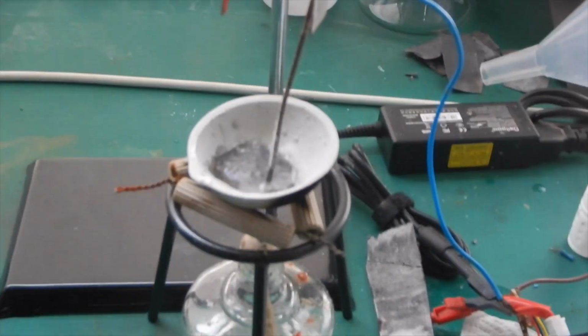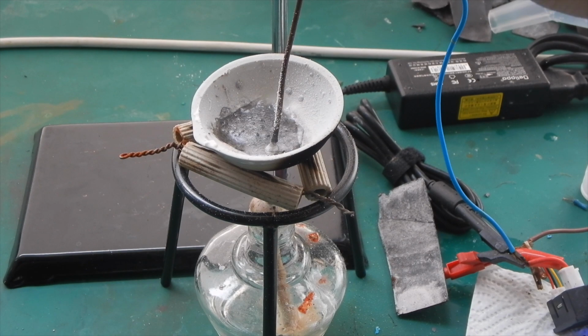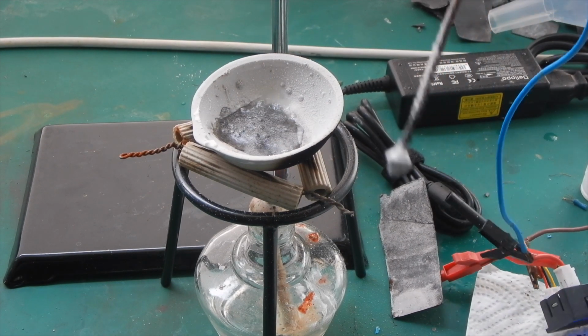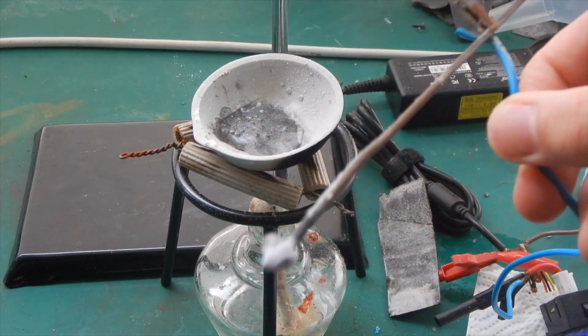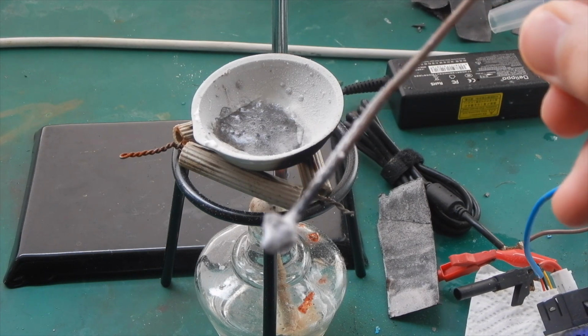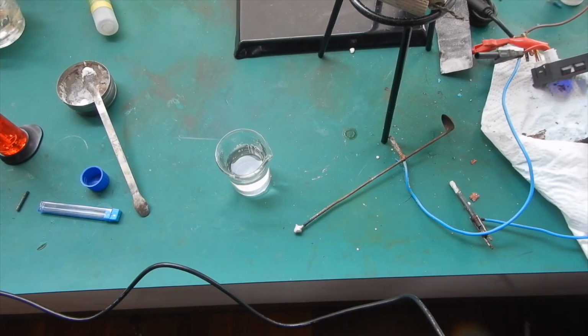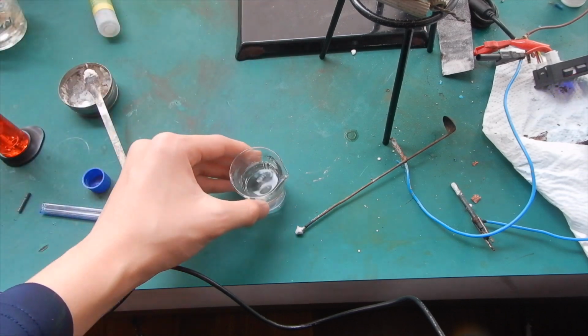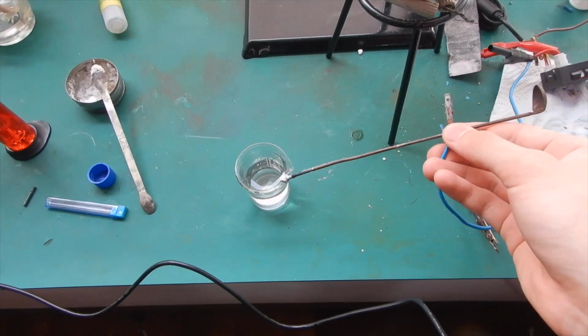I stopped the cell and took the iron handle off the stand. You can see that it is coated with a bunch of white salts. When the electrodes are taken out, there is a little bit of shiny lithium metal floating on the melt. After the iron handle has cooled down, I put it into some water with a little phenolphthalein added.